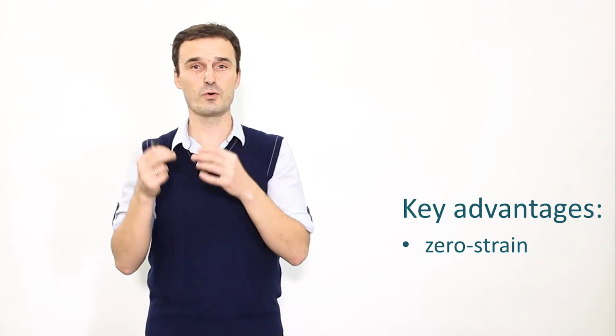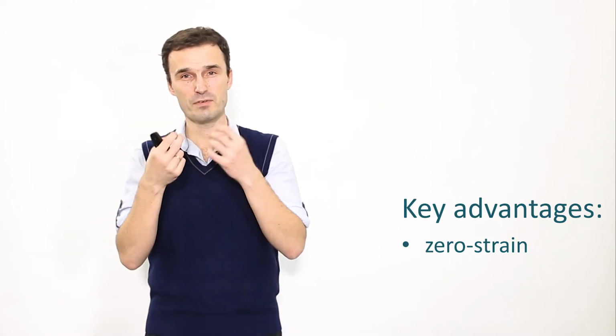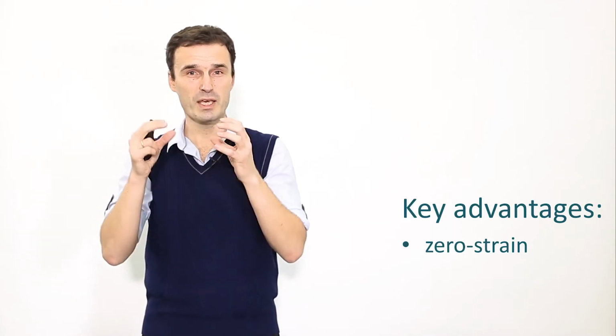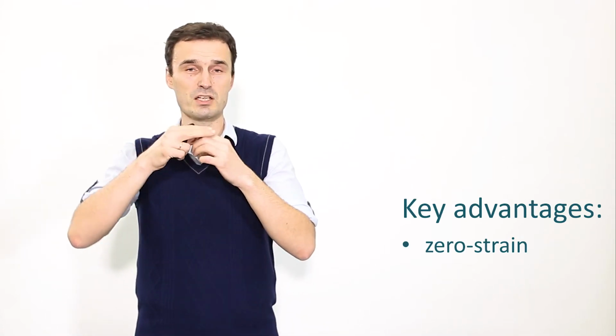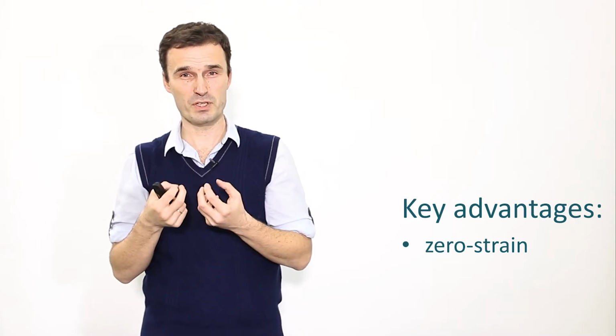Lithium titanate is often named a zero strain material. It means that during lithiation and delithiation, so inserting and extracting lithium ions, it almost doesn't change its volume, it stays the same. So you have no mechanical stresses, you have no loss of conductive contact and so on and so forth. So it's a very important property.